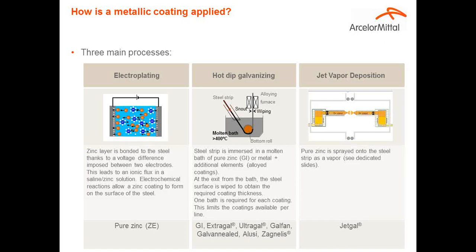Second way to apply a coating is by hot dip galvanizing. In hot dip galvanizing, as you can see on the drawing, the steel strip is immersed in a molten bath of pure zinc or in a bath of metal plus alloying element, as mentioned before in the case of alloyed coating. At the exit of the bath, the steel surface is wiped and we obtain the required thickness of the coating desired. This is how we apply the coating GI or Extragal in the case of ArcelorMittal products, Ultragal, Galfan, Galvannealed, Alusi and Zagnelis, some coatings that we will see afterwards.